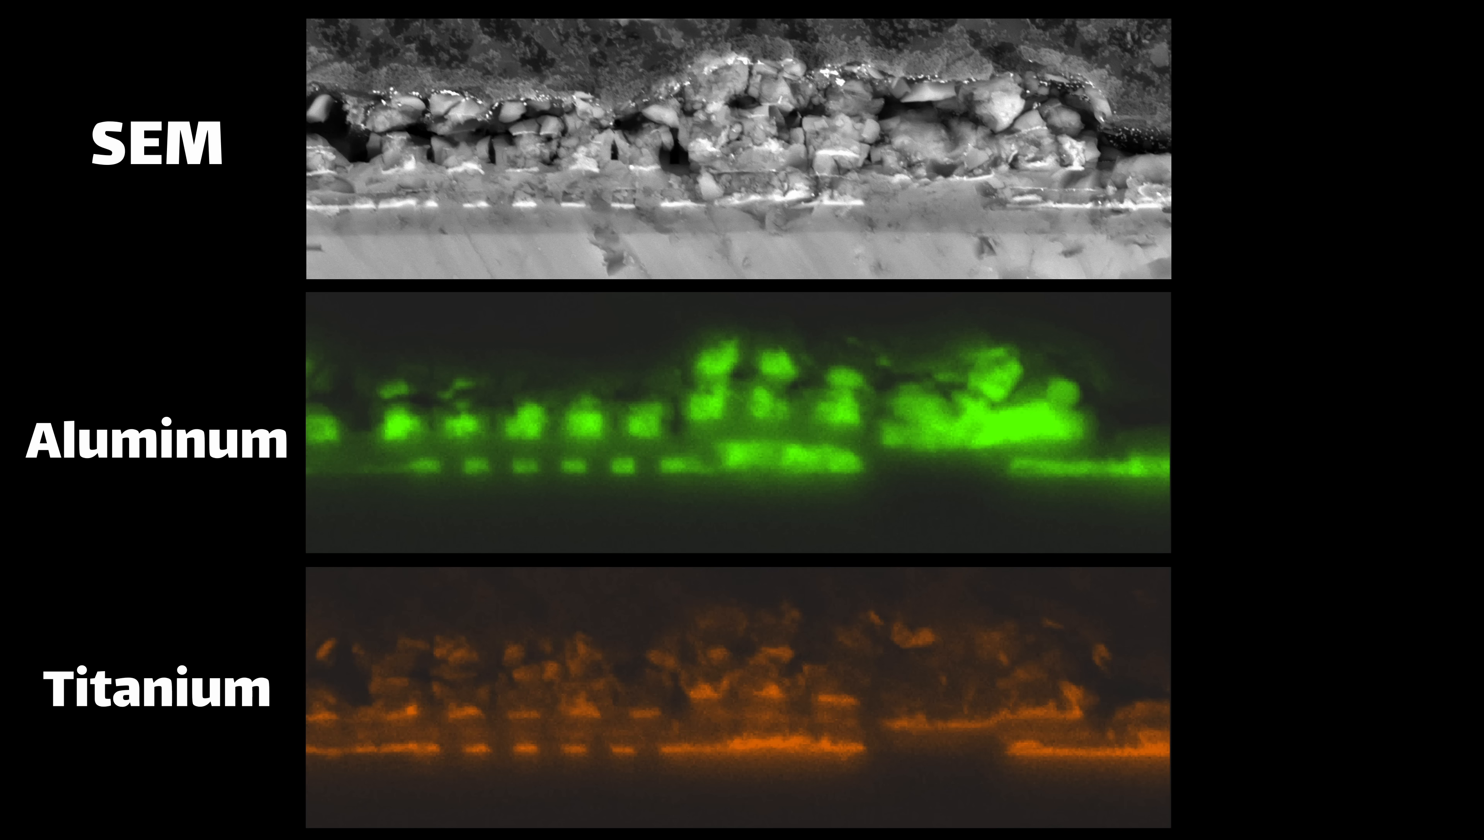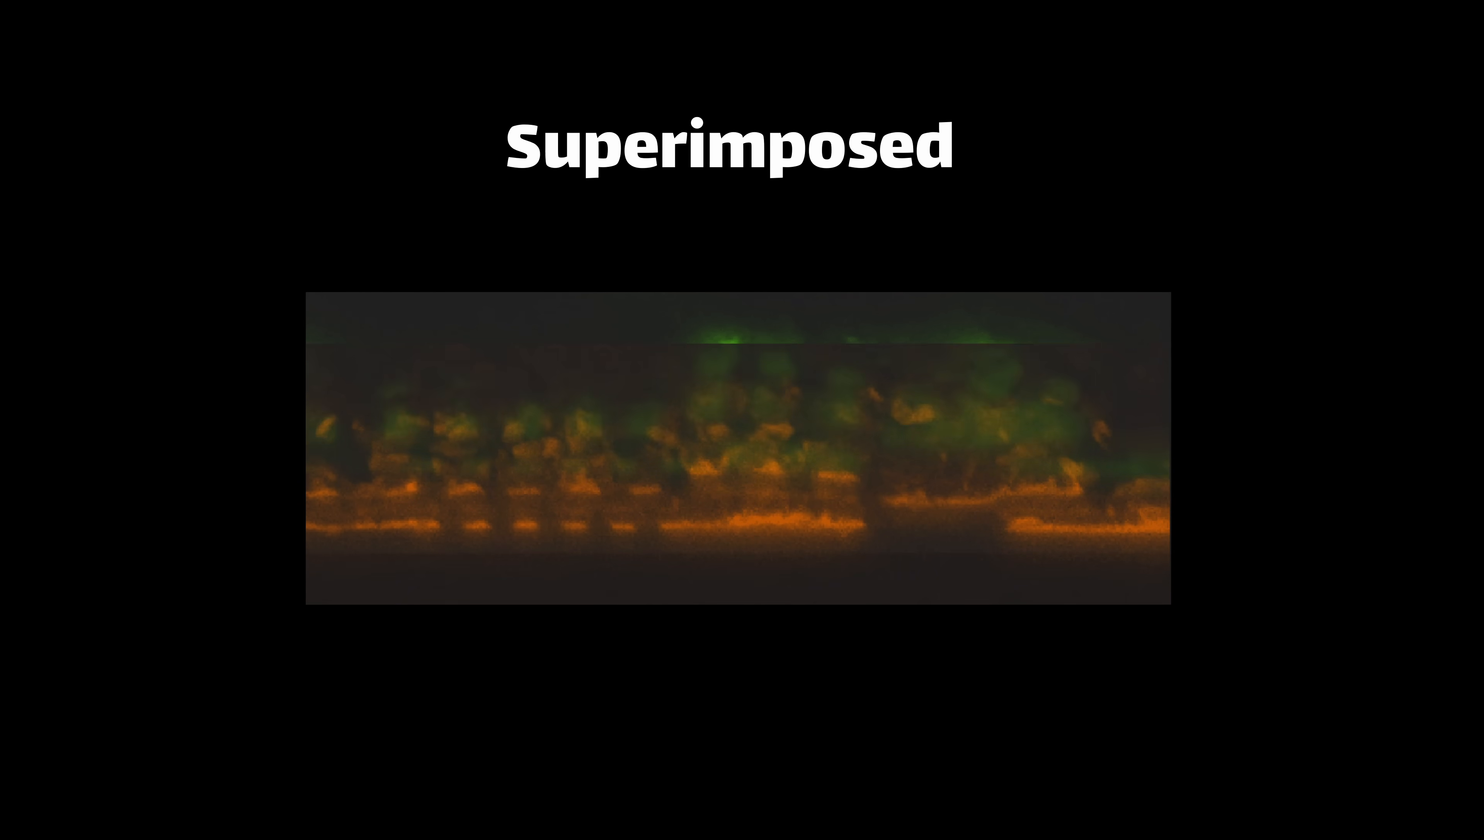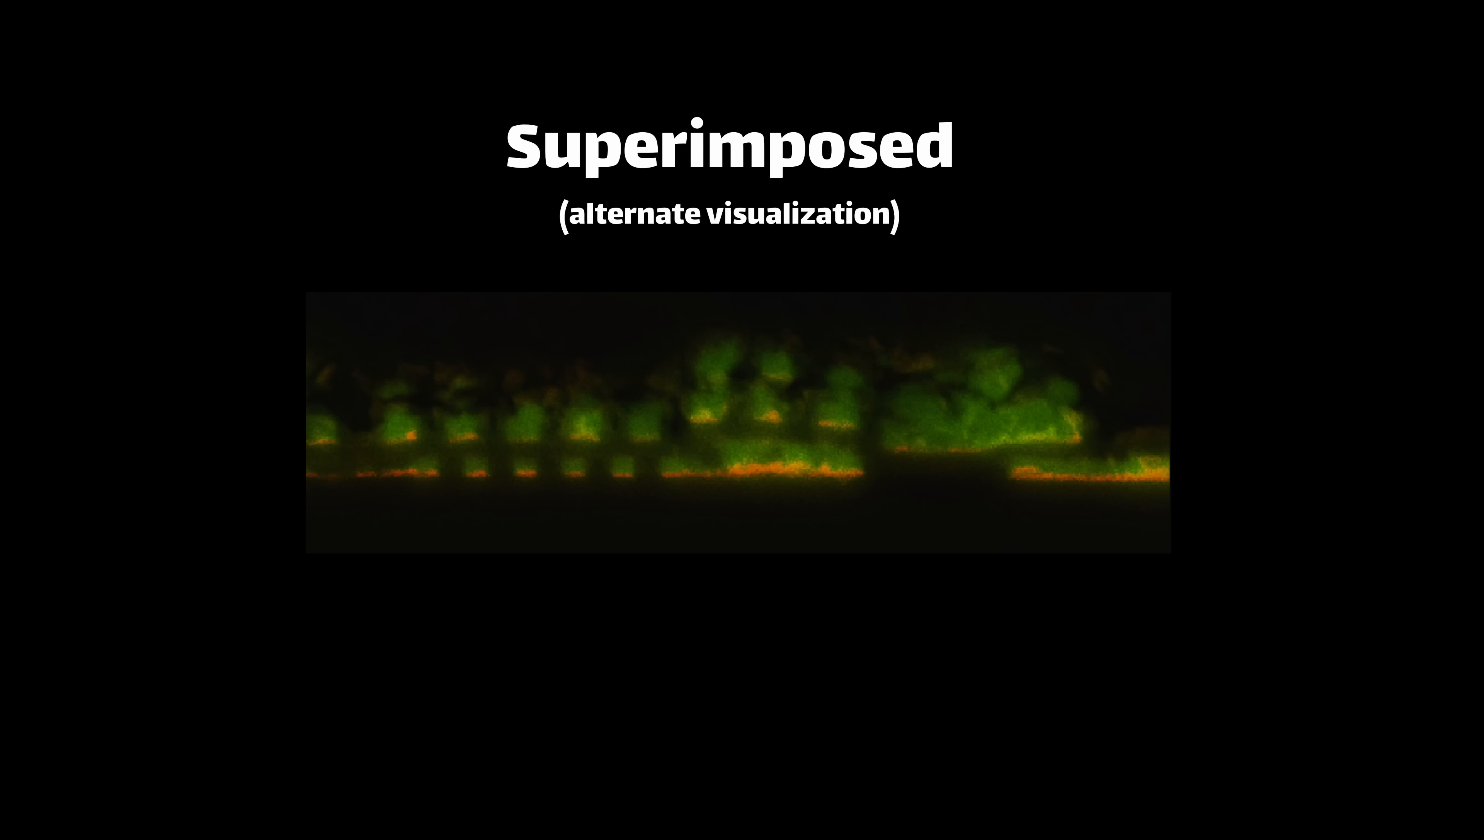If you look closely, you can see that it shows up underneath the aluminum in a few different locations. It sticks well to oxide, and other metals like to stick to it. So a thin layer of titanium is often deposited to help other metals stay in place or stick to surfaces they wouldn't normally like.